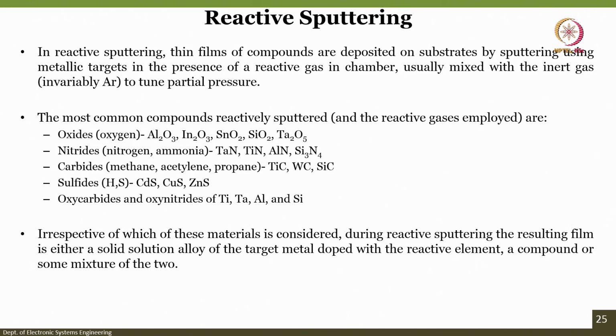Now, let us come to the last one, which is reactive sputtering. In reactive sputtering, thin films of compounds are deposited on the substrate by sputtering using metallic targets in the presence of a reactive gas in the chamber, usually mixed with the inert gas, invariably argon, to tune the partial pressure. So, the most common compounds reactively sputtered are oxides in the presence of oxygen, nitrides with nitrogen and ammonia, carbides with methane, acetylene, propane, sulfides, oxycarbides and oxynitrides. So, there are several materials which we can deposit with the help of